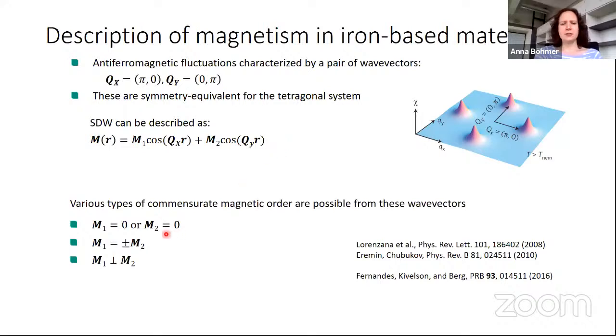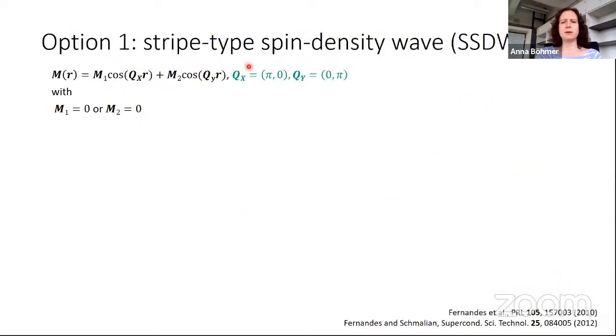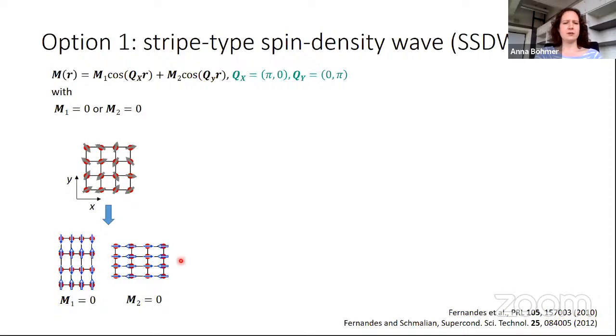And it turns out you cannot have any values for these two order parameters. They have relations. There's 3 options. And let's go through these 3 options quickly. The first one is our stripe spin density wave that you can see here. It is found when one of these order parameters is 0. So then you have just one of these cosine functions. So cosine along one direction, the other direction is 0. So ferromagnetic in one direction, antiferromagnetic in the other. And depending on which one of these amplitudes is 0, you find the left sort of stripe or the right one. So there's a choice here.